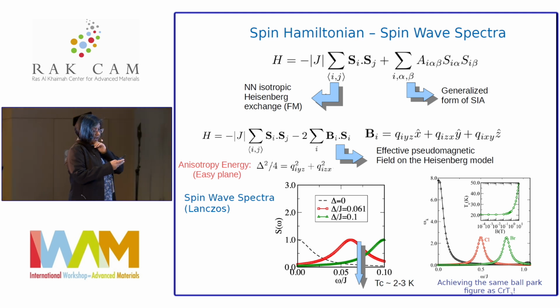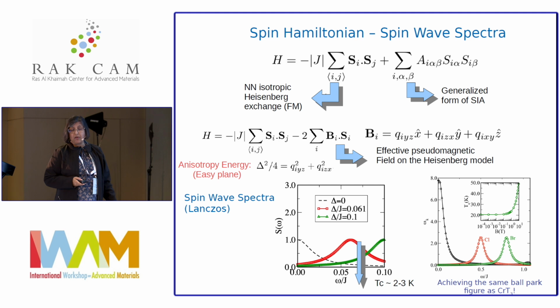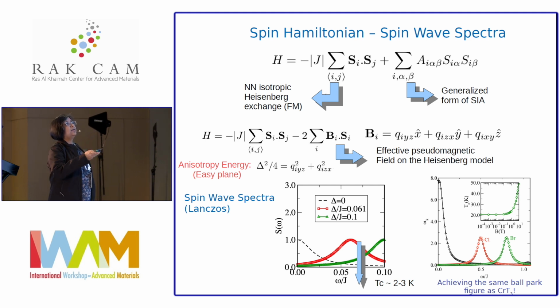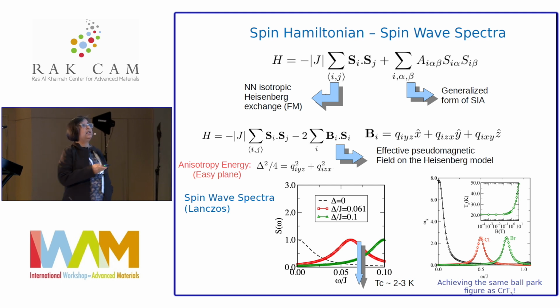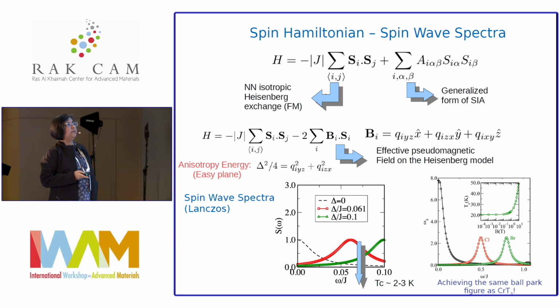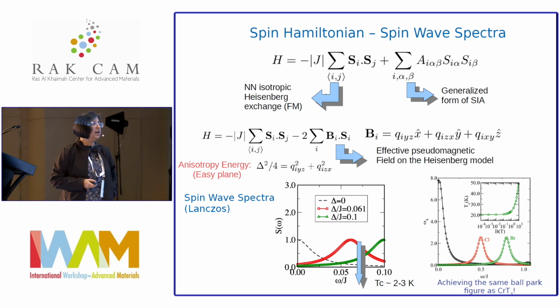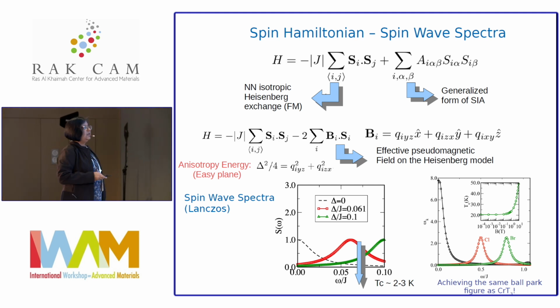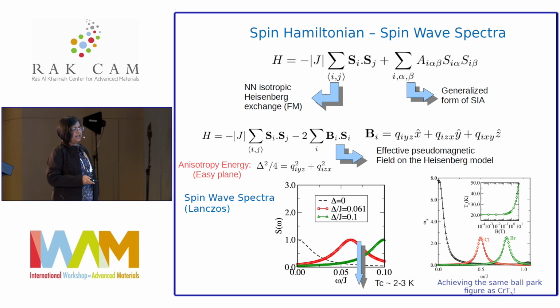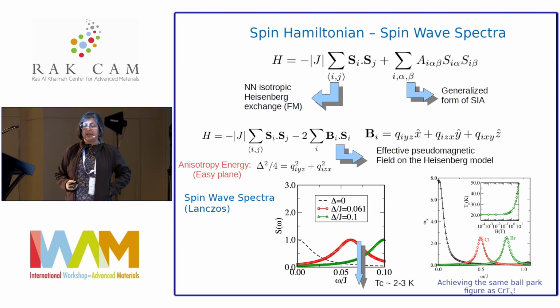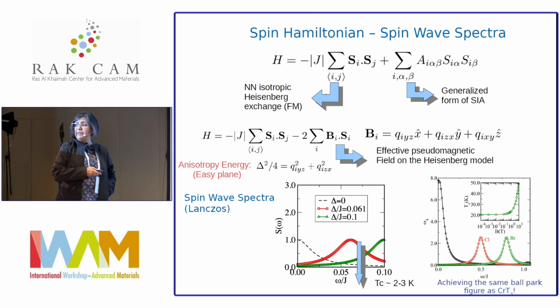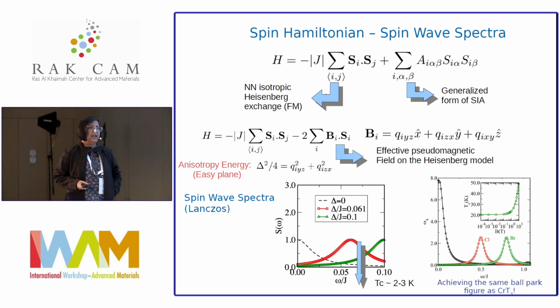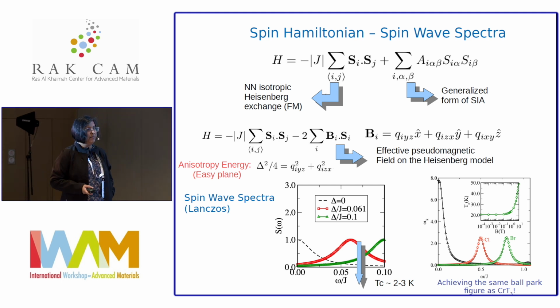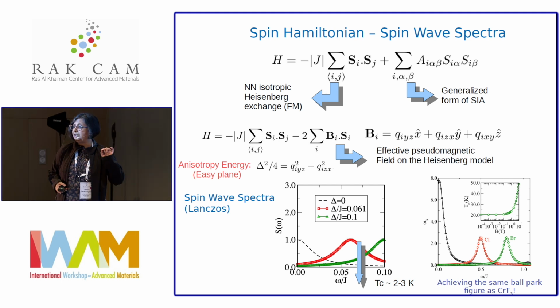Well, we made a model. We calculated the magnetic exchanges, which turned out to be ferromagnetic, as I argued just from the orbital symmetry point of view. And we also calculated the magnetic anisotropy. We considered even a generalized form of this anisotropy, which acts like a pseudo-magnetic field in the Heisenberg model. And then solving the spin wave spectrum through a Lanczos method, we find for the copper system the TC is pretty small, although it will order ferromagnetically at some 2 to 3 Kelvin. But for the chromium system, the TC can be as high as 40 Kelvin, in the same ballpark as chromium iodide, if you apply a modest amount of magnetic field. Without the magnetic field, the transition temperature itself is 20 Kelvin.